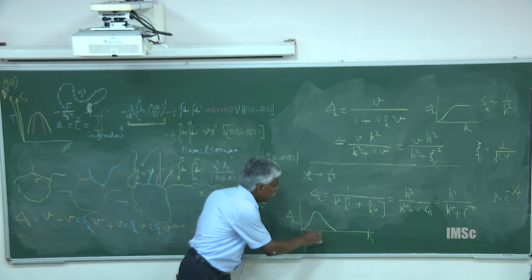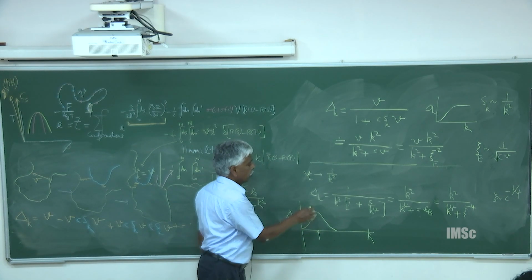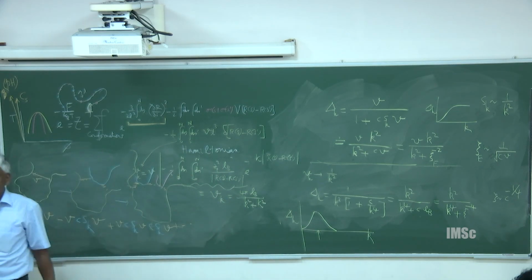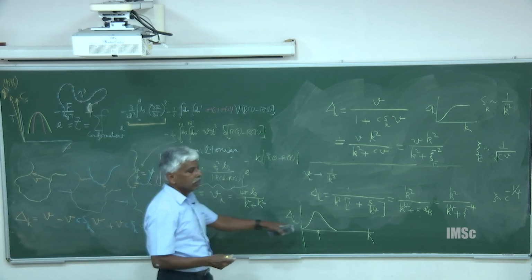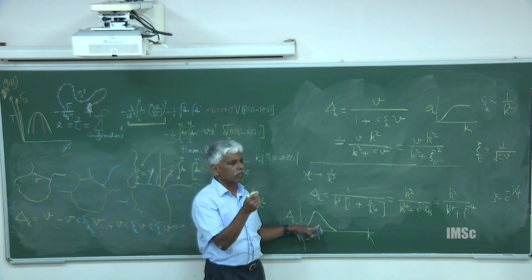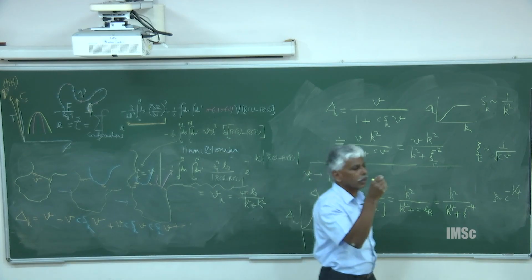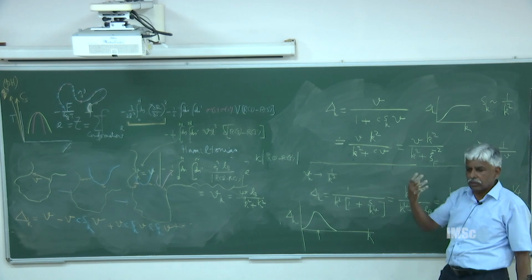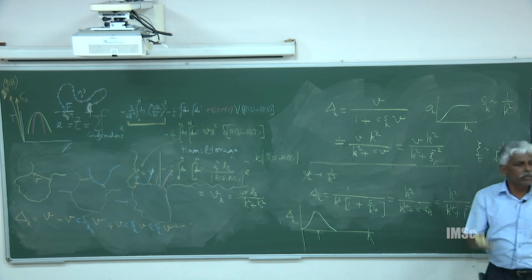That means there is some intermediate length scale, and you can work out where the peak is going to be. That means there is going to be structural evolution where a finite size structure is selected spontaneously. So when electrostatics is important, you will have what we call the polyelectrolyte peak. We observe this experimentally, it is well established, and it agrees with theoretical calculations. So there will be a spontaneous selection of certain sizes, certain length scales, even in the daughter phase.